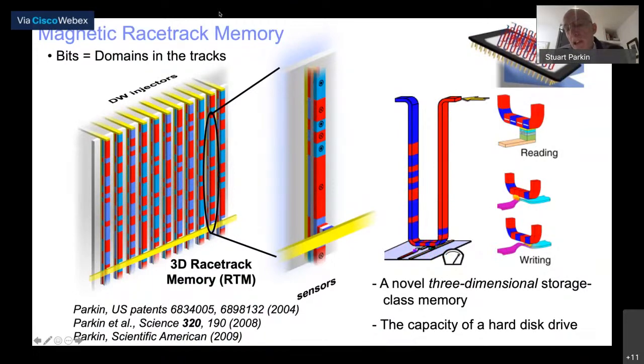And the basic fundamental principle that makes racetrack interesting is that when you pass current into these nanowires, you can move all of the domain walls around the wire. So you bring the information to a reading device and to a writing device that is integrated into the racetrack. That is the idea. If we could build these vertical racetracks, we could easily achieve the capacity of a magnetic disk drive in a completely solid-state device without any moving parts. So it would be very reliable, very high performance. It would be 1 million times faster than the magnetic disk drive, and of course use much less energy.